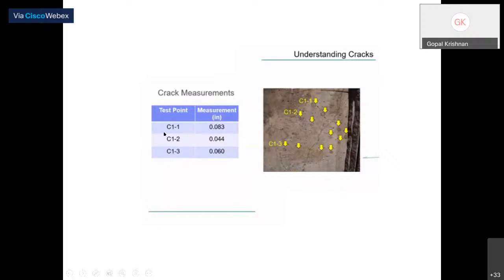Based on that, we can report crack 1 as 0.083, crack 2 as 0.044, and crack 3 as 0.060. We can report the cracks so that we can take the appropriate measures to repair them.